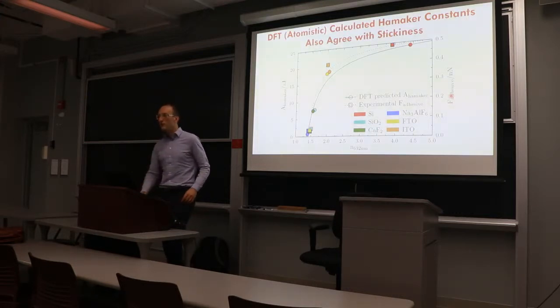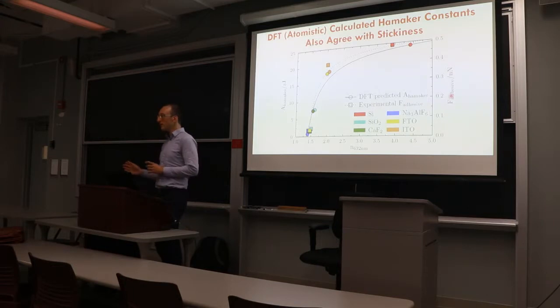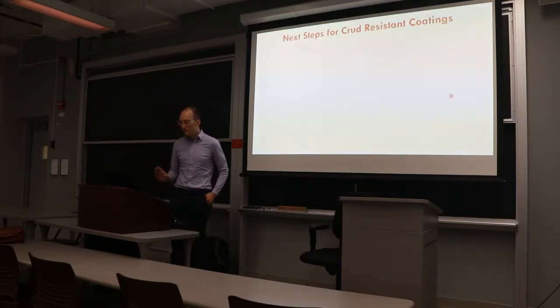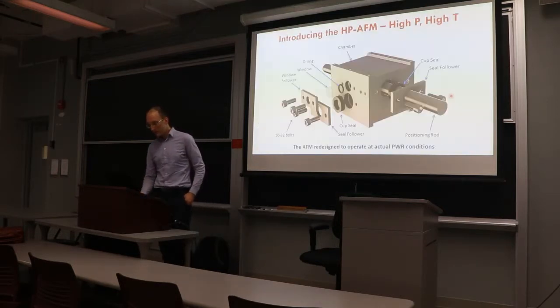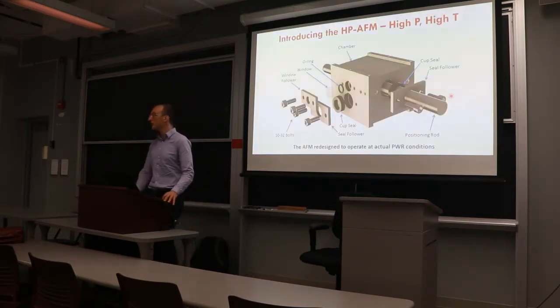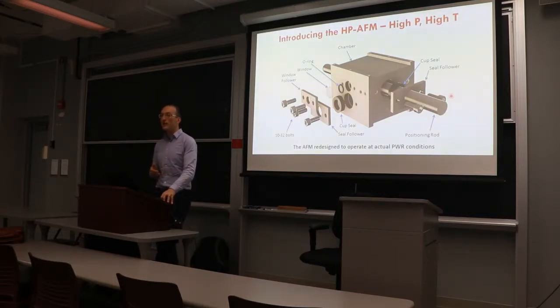Yeah. And a little preview of what's to come. There's one experimental gap that I haven't mentioned, and that's what is the actual adhesion force at reactor temperatures? No one's ever measured it because no one's ever been able to. So we've also constructed monstrosity number 2, a high pressure, high temperature atomic force microscope. We built an AFM that goes to 150 atmospheres, 350 Celsius, and in liquid cell. So we're actually able now to characterize how sticky things are in reactor conditions.